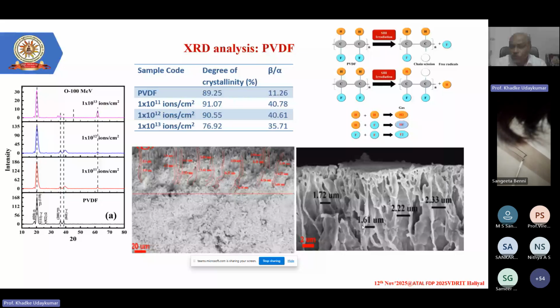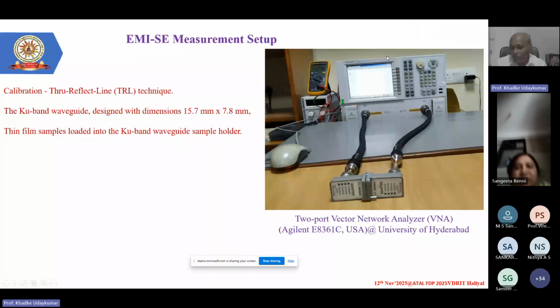And even the chemical composition: what happens to the chemical composition the moment the ion beams hit the surface? Obviously damage takes place. What kind of damage will take place? There will be breakage of the bonds between the ions, or free radicals will be generated, and those free radicals will get eroded outside in gaseous form. They will get exposed, they will get outside, and you will see that erosion will take place, and nice columns will be created. And these columns have been shown in the picture. Well, this is the setup we use in order to measure the EMI SE.